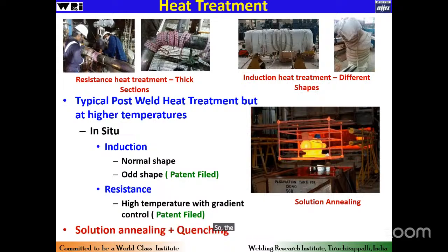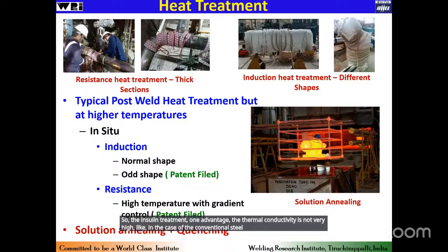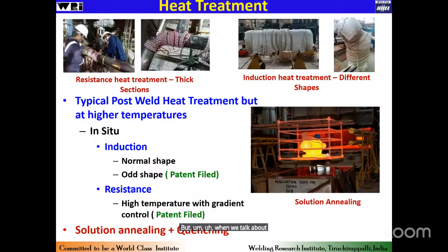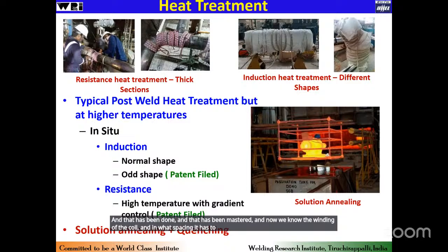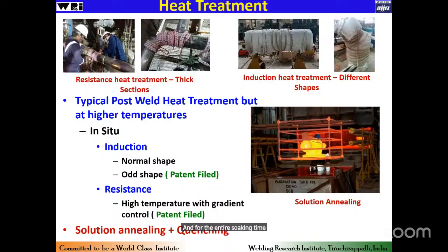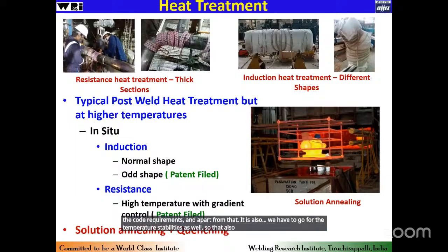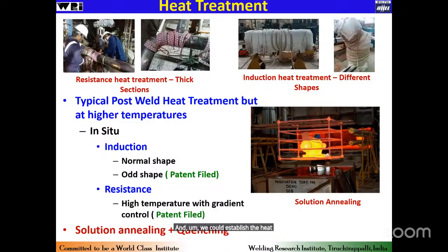So the in situ heat treatment, one advantage, the thermal conductivity is not very high like in the case of the conventional steel material. But when we talk about these grades of thicknesses, in these grades of materials, we needed higher capacity facilities for the in situ heat treatments, and that has been done and that has been mastered. And now we know the winding of the coil, in what spacing it has to be done for what kind of configuration, so that we'll be able to achieve the desired temperature and for the entire soaking time, meeting the conditions of the code requirements. And apart from that, we also have to go for temperature stabilities as well, so that also has been controlled. And we could establish the heat treatment for such grades of materials.